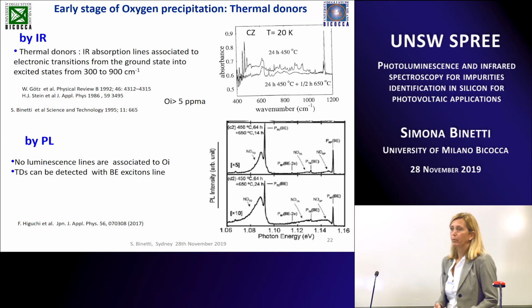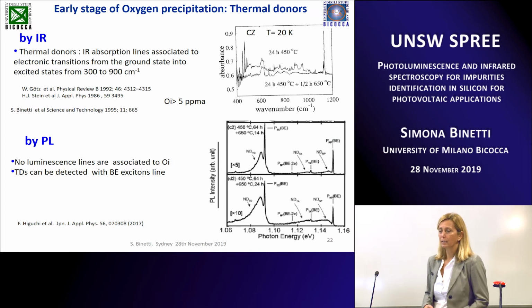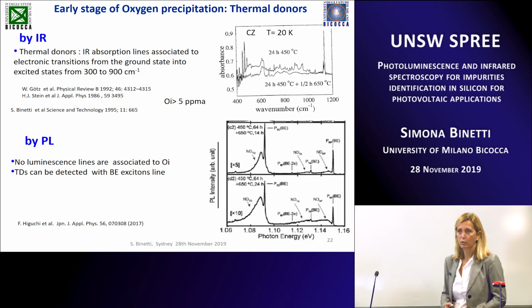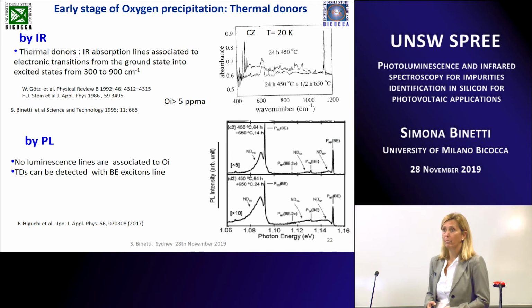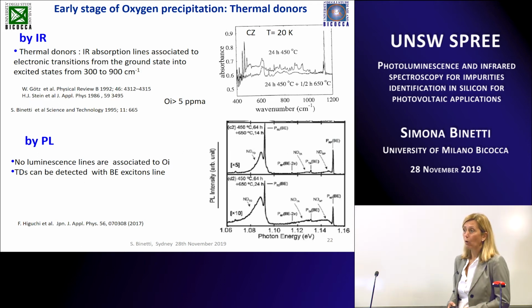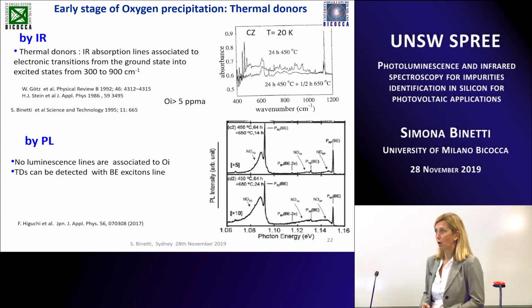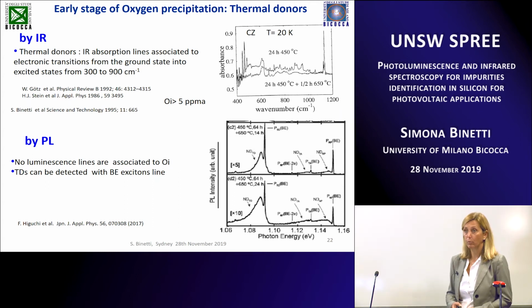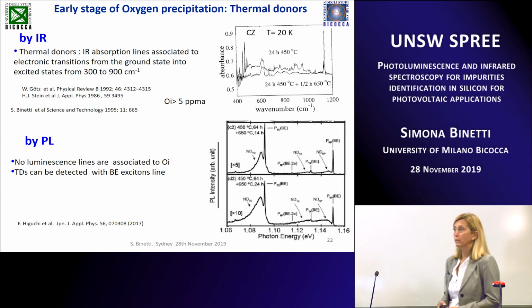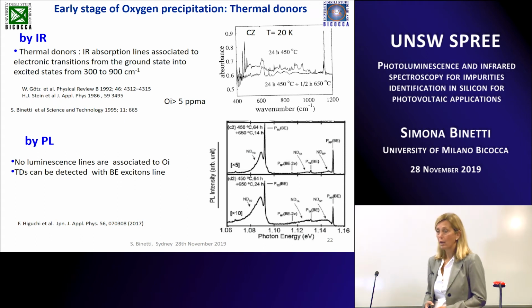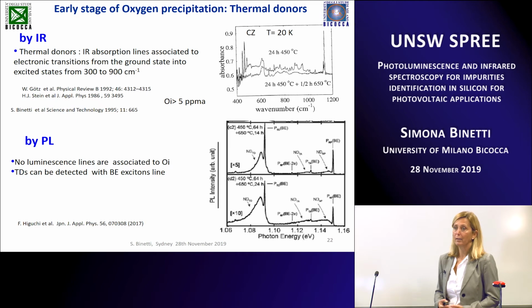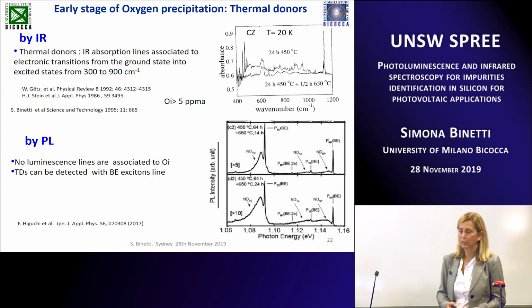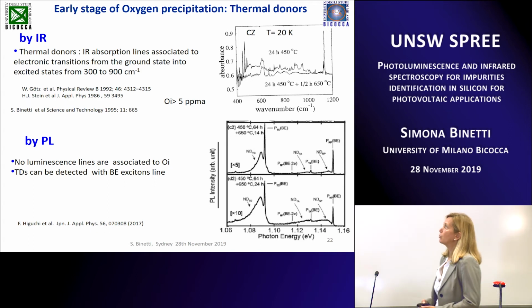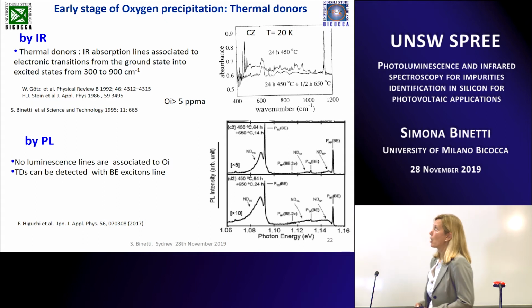Sometimes it's very important to have some technique that is able to detect the early stage of oxygen precipitation, because I remind you that silicon is always a solid solution of silicon and oxygen, both in solar grade but also in multicrystalline silicon. So it's always a supersaturated solid solution. That means that with any thermal treatment you can induce precipitation and the formation of nano or micro or large precipitates. So sometimes it's useful to know if you have some oxygen precipitation in your material.